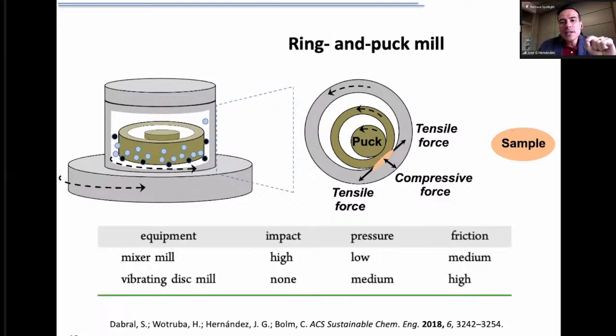And what is the reason for that? Well, as I said before, by vibrating this mill, you achieve friction in higher quantities compared to the impact, which is actually none. Whereas when you do grinding by ball milling, you have plenty of energetic collisions, but the friction is minimum. Sometimes there is shear force, depending on how the ball is moving, the trajectory within that container, whereas you have one or two balls. But most of the time, what you have is impact when you do reactions in mixer mills. So this could be an option to achieve higher directionality by milling techniques, which could be applicable for polymer mechanochemistry.